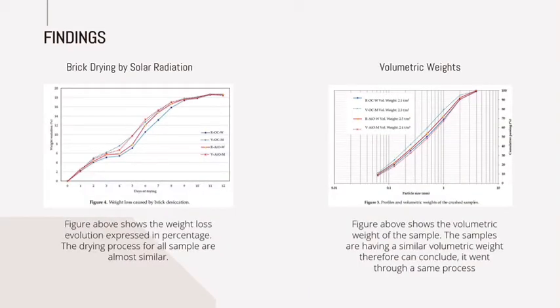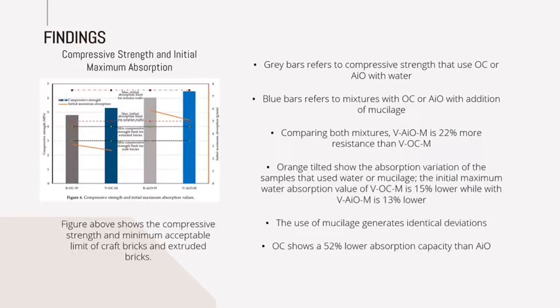This is the finding where the first one is the brick drying by solar radiation. We can see the weight loss evaluation and next, the volumetric matrix. And the next finding is for the compressive strength and the initial maximum absorption. In the picture, we can see that the grey bar refers to compressive strength, the blue bar refers to the mixture with OC or AIO with addition of mucilage, and comparing both mixtures, VAIOM is 22% more resistant than VOCM.